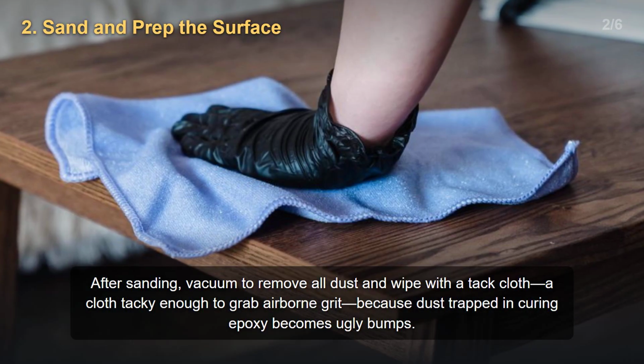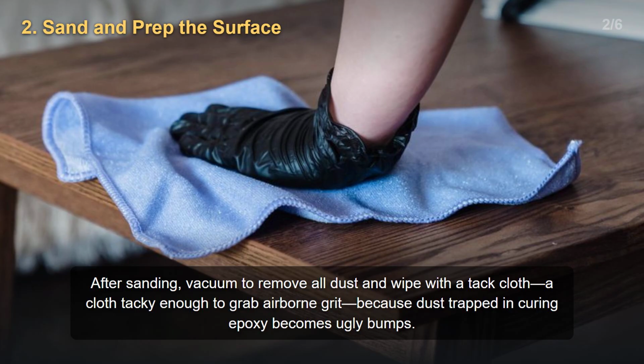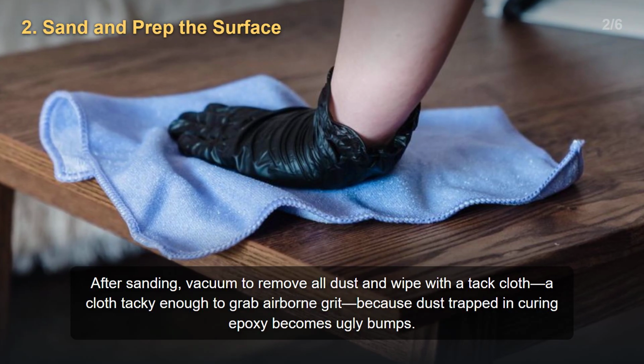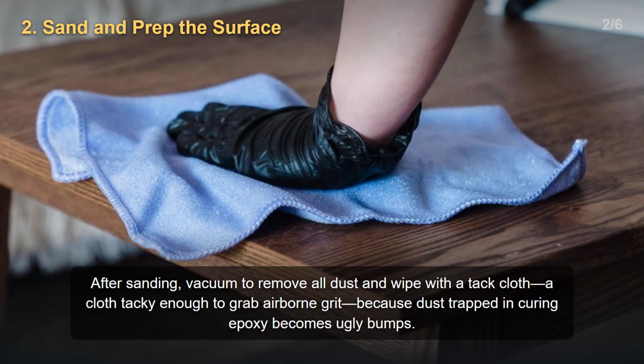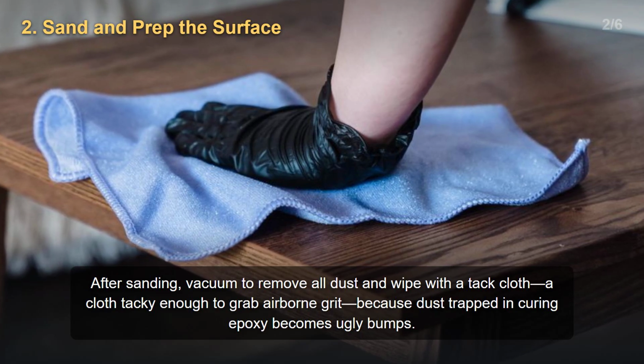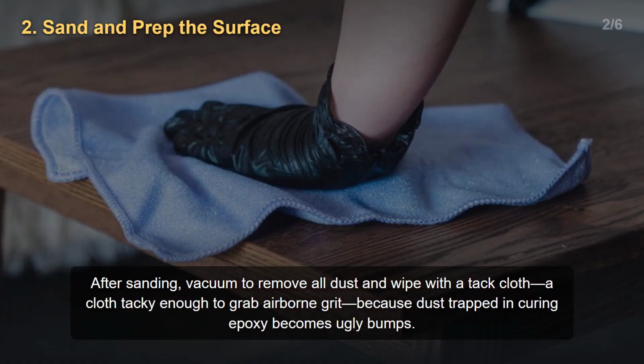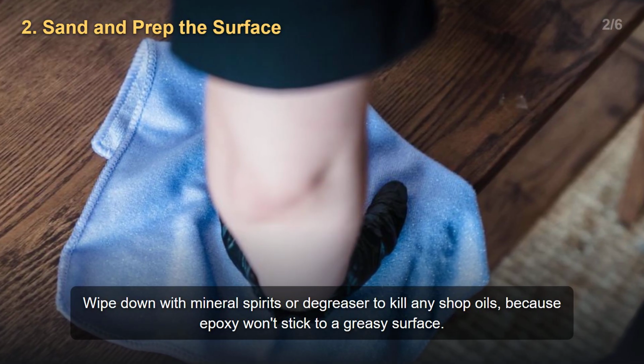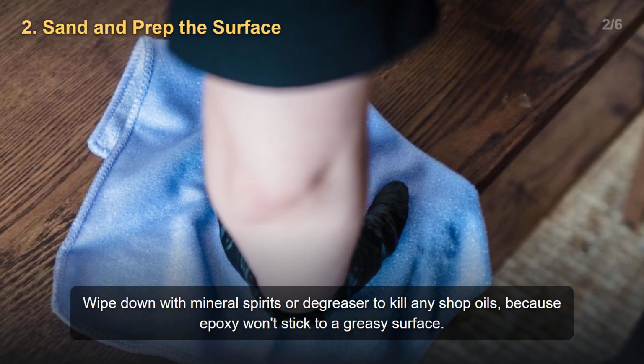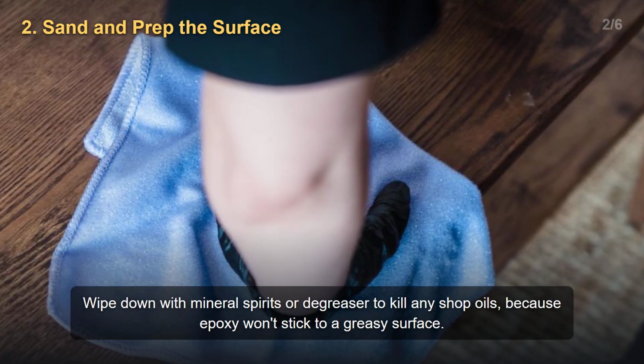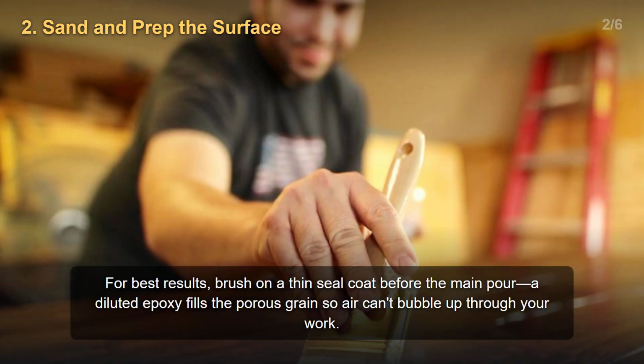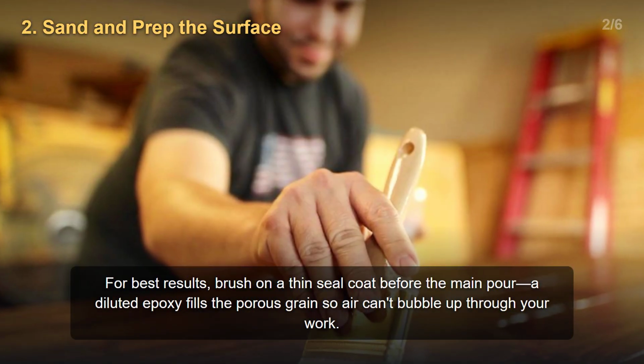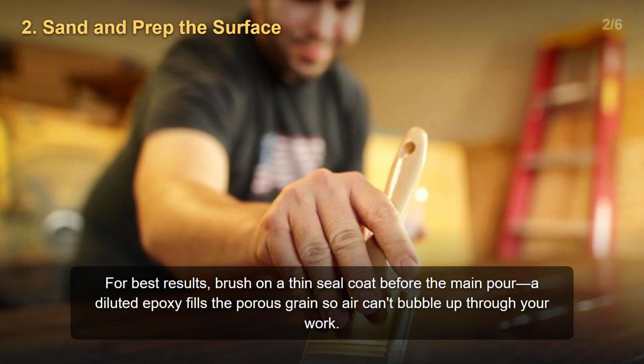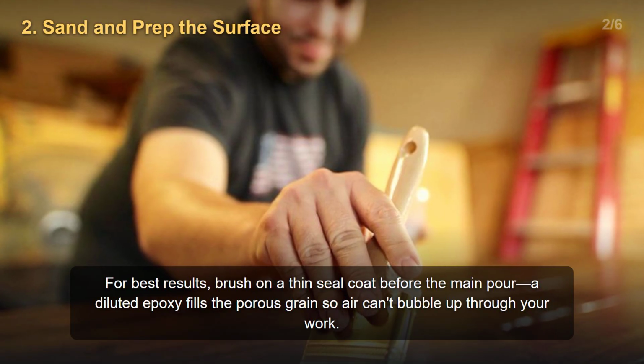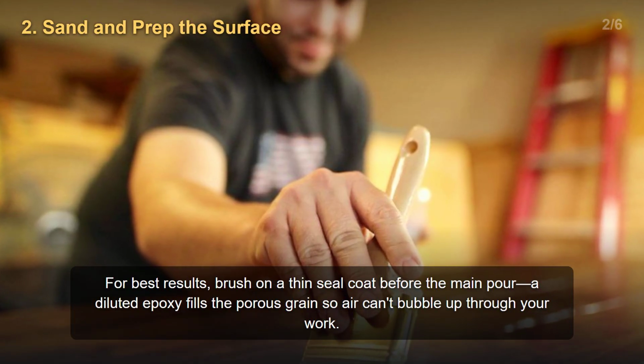This key gives the epoxy texture to grip, and skipping it dooms the bond before you pour. After sanding, vacuum to remove all dust and wipe with a tack cloth, a cloth tacky enough to grab airborne grit, because dust trapped in curing epoxy becomes ugly bumps. Wipe down with mineral spirits or degreaser to kill any shop oils, because epoxy won't stick to a greasy surface. For best results, brush on a thin seal coat before the main pour. A diluted epoxy fills the porous grain so air can't bubble up through your work.